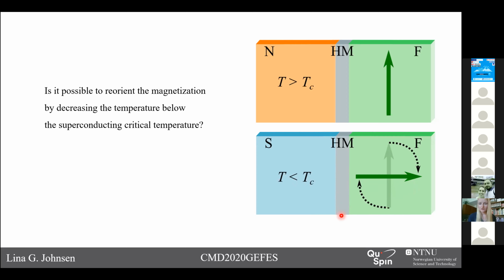Previously, it has been shown that by rotating the magnetization of the ferromagnet, you can change the critical temperature of the superconductor. We wanted to look at the reciprocal effects. That is, is it possible to reorient the magnetization by decreasing the temperature below the superconducting critical temperature? That is, can we use the superconducting phase transition to affect the magnetization direction of the ferromagnet?